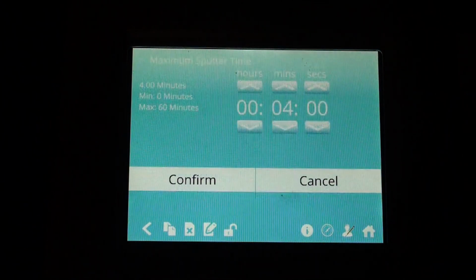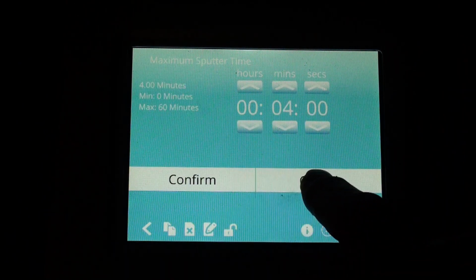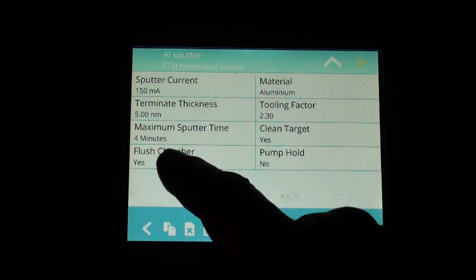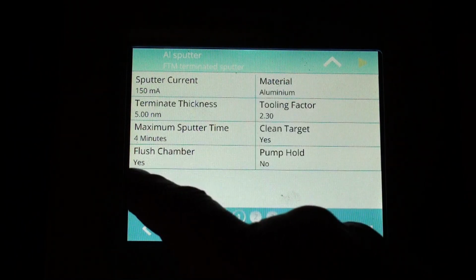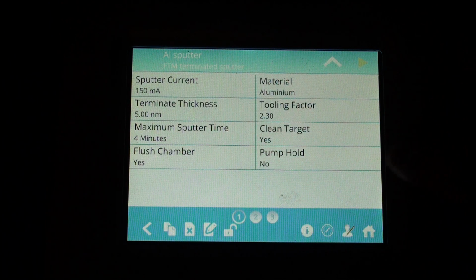Aluminum tooling factor, we're not going to play with that. Flush chamber, maximum sputter time. You change this depending on your thickness of coating. Some people that want 100 nanometers, that takes quite a bit of time, even at maximum power, but we're not going to change this. 4 minutes is adequate for 5 nanometers of aluminum.